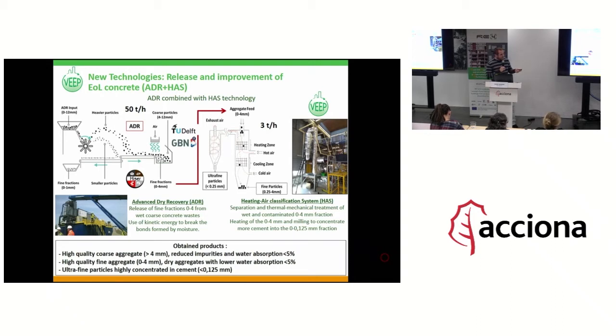So the products obtained from this combination of technologies are coarse aggregate with reduced impurities and water absorption, fine aggregate also with reduced water absorption and without impurities, and ultrafine particles that will be employed as supplementary cementitious material, in order to replace the cement of the concrete formulation.